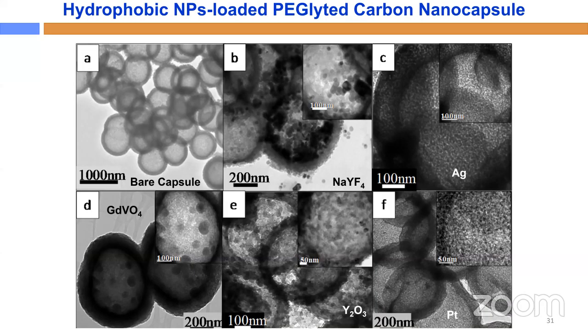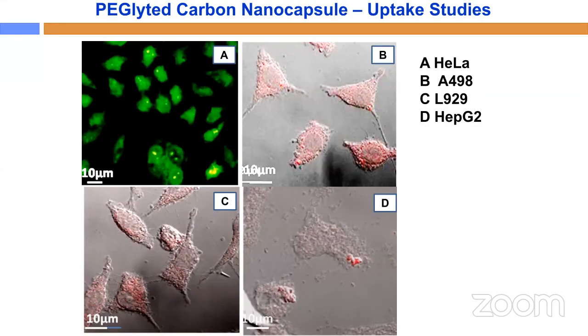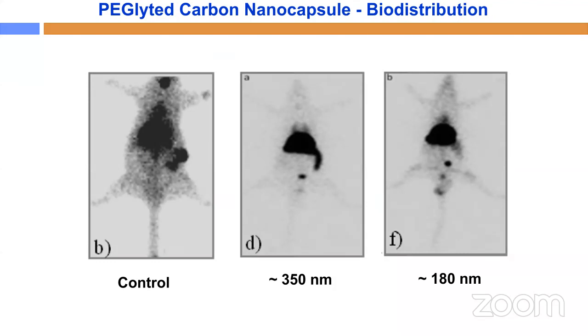We have taken transmission electron microscope images. In B, C, D, different kinds of hydrophobic nanoparticles are shown loaded inside the carbon capsule. Even with this, we have done one hydrophobic and one hydrophilic, so both types of nanoparticle have been loaded inside the carbon capsule. As said earlier, once it is done, we have done the uptake imaging studies. All the green and red emission is coming from the nanoparticles, done with different types of cancer cells.